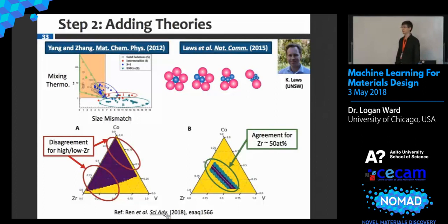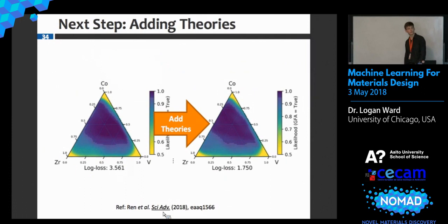So this is particularly interesting to us because it actually showcases another advantage of machine learning. By incorporating these models as inputs into our machine learning representation, we can effectively identify which are the alloys for which each of these theories are more predictive. We found that this actually has a small benefit to our model for this particular system because our machine learning model was already predicting metallic glasses in the same region. So given this model that now incorporates theories and processing conditions as an input,